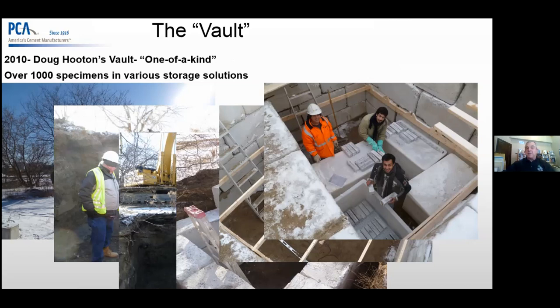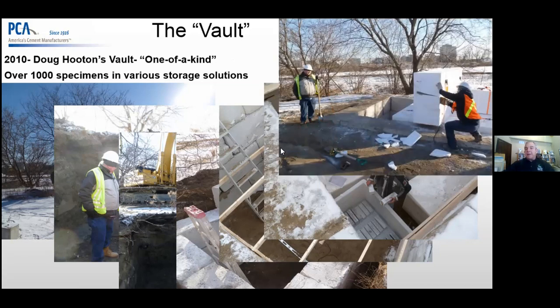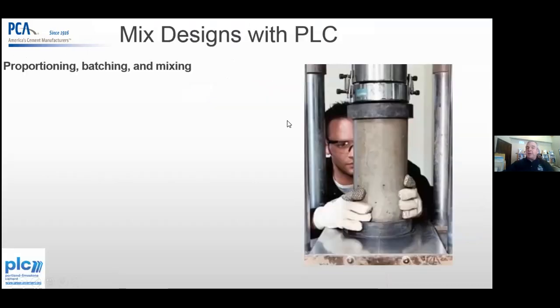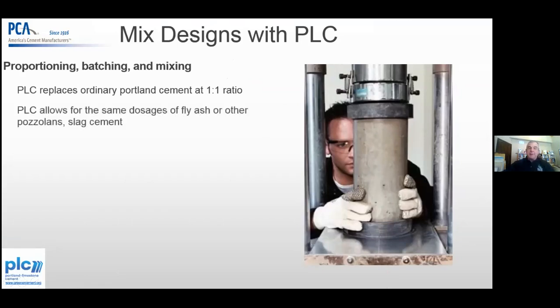There's not any more of it in the world, and it's been going on for 10 years. And then of course we just cover it back up every year until we have to open the vault up again the next year. I'm going to get into his results in just a little bit here. But mix designs with PLC, everybody asks us, what do you do? Well, what our experience has been, and we verified it, is that you just replace ordinary Portland cement at a 1-to-1 ratio. There's no compensating for anything else. We've discovered that you can use the exact same replacement levels of fly ash, slag, or other pozzolans without issue.